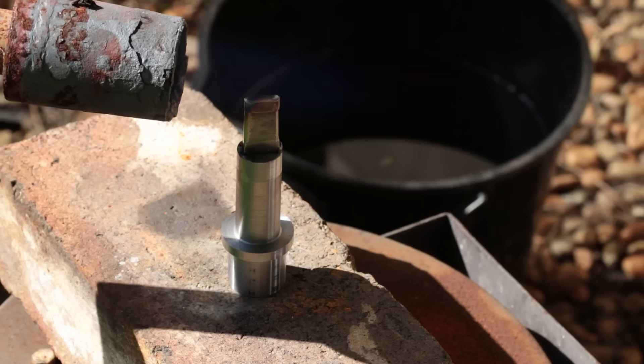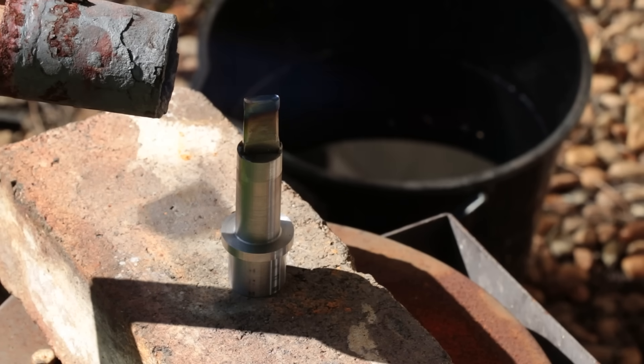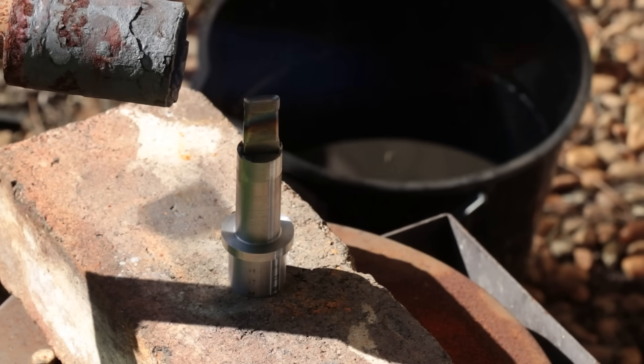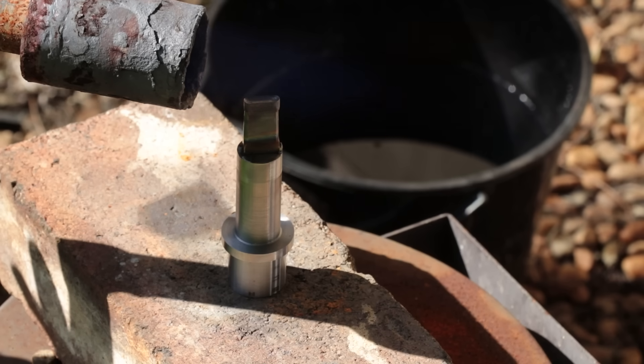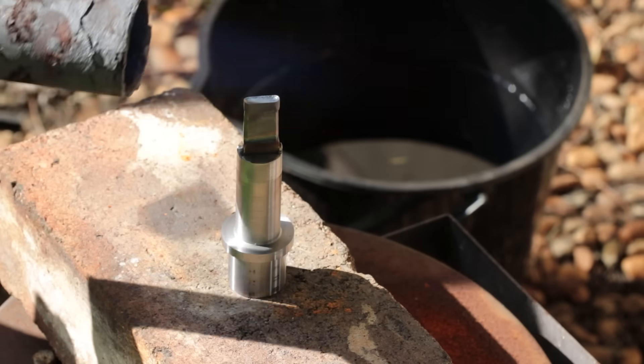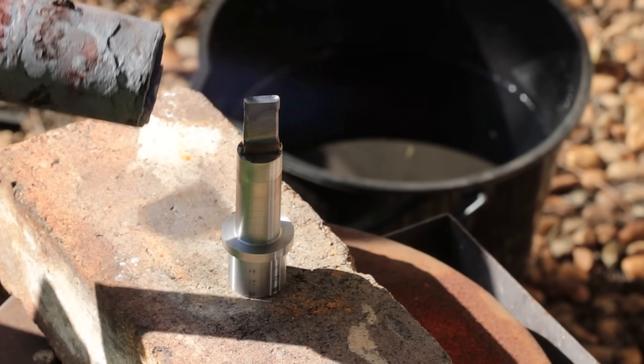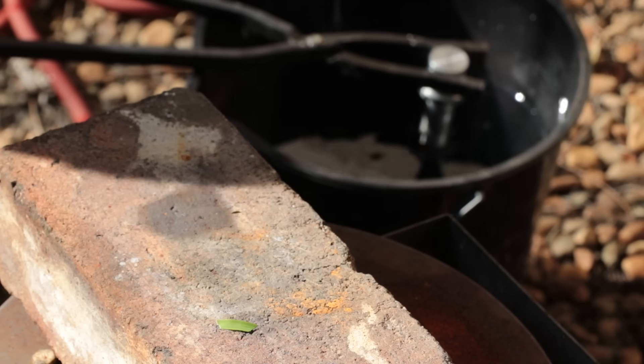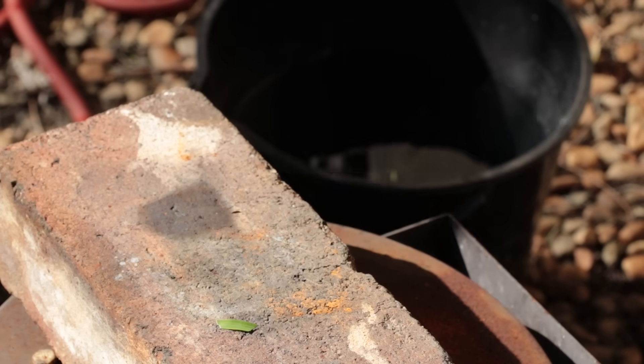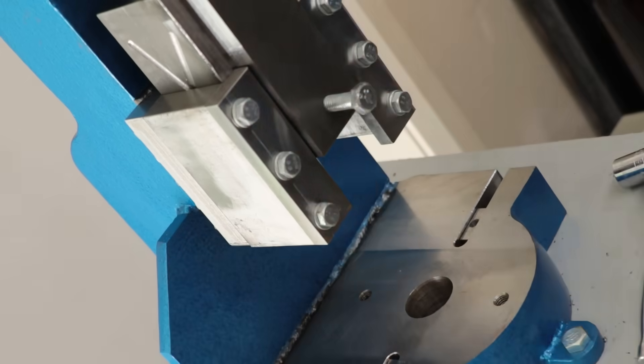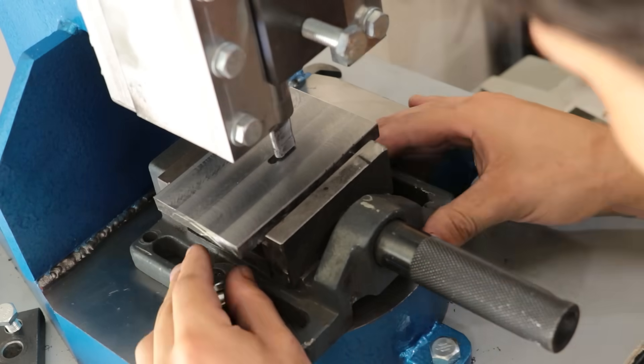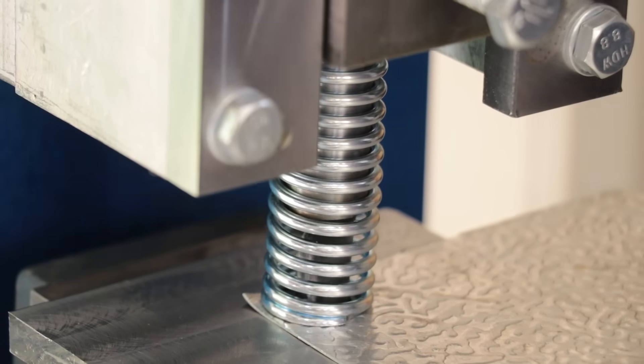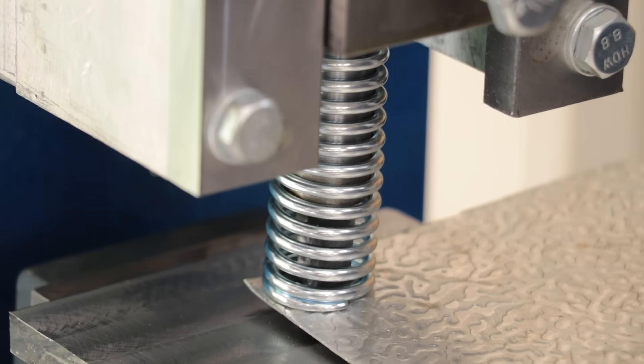The final thing left to do was to quench and then temper the tip of the cutter in order to harden it. Now, even though this is O1 tool steel and it's designed to be quenched in oil, most of the time I simply quench it in water, mostly because you get very similar results from doing it either way. And quenching it in water ends up being a lot easier to set up and easier to clean up.